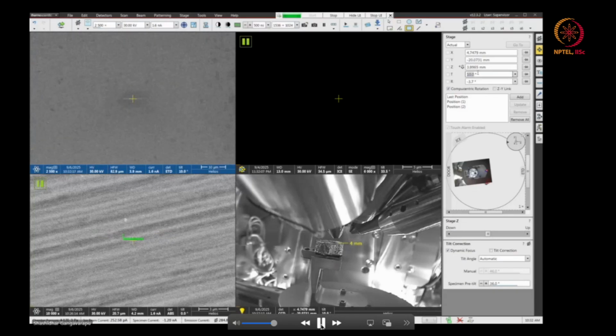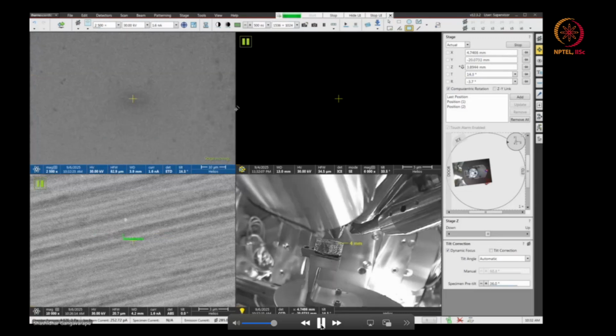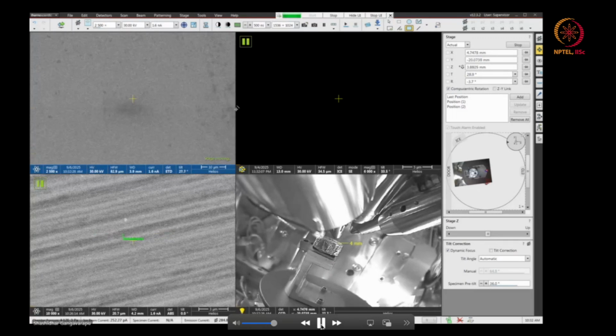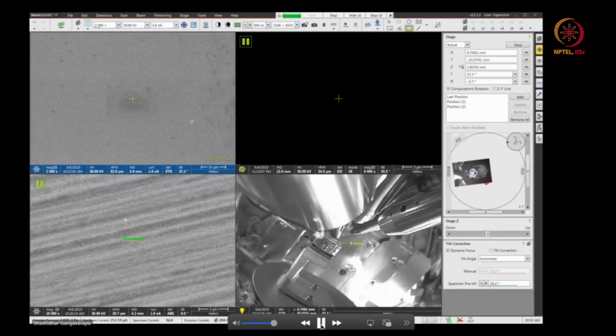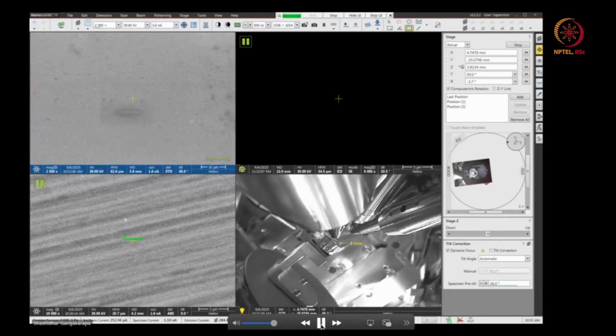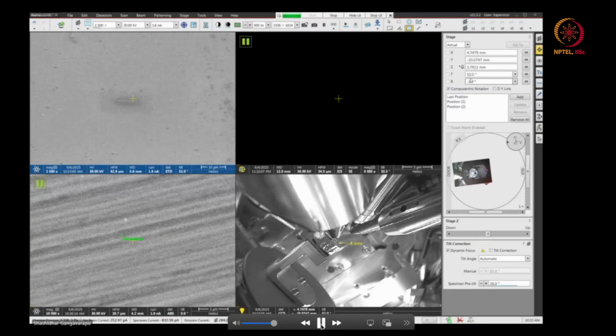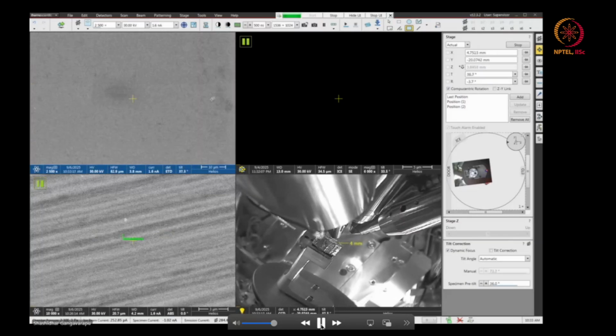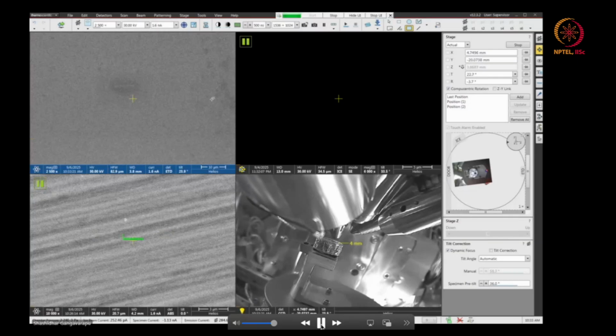At the eucentric height, our electron beam and the I beam meet at the same point. So now I tilt to 30 degrees to check. Now it moves a little bit, so again I use the Z height and bring it to the center. Next I go up to 52 degrees, because at 52 degrees my ion beam column is perpendicular to my sample. Again I adjust the Z height by stage movement, and now my eucentric is done. Now I go to 0 degrees, and you can see my feature is almost at the center. It changes a little bit, but it's almost center.